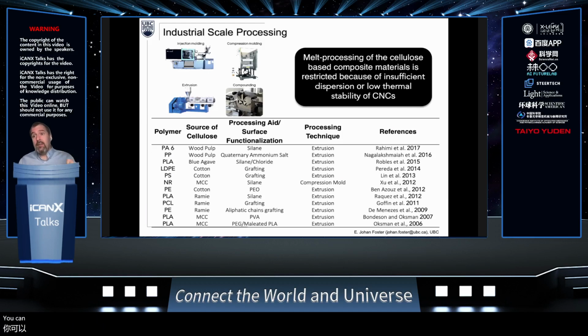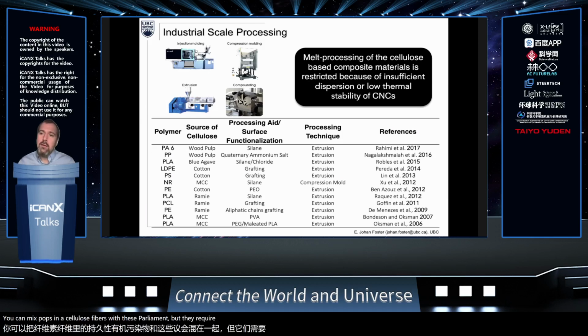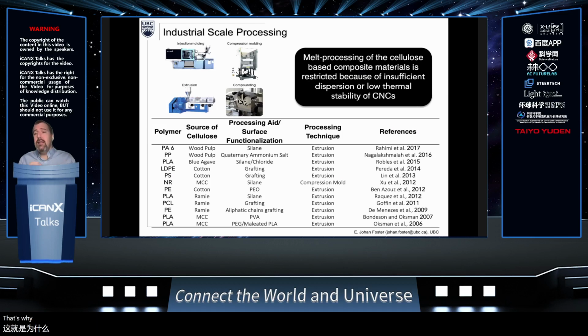You can mix pulps and cellulose fibers with these polymers, but they require some sort of modification. Okay, you can modify the surface with silanes. You can modify them with salts. You can graft polymers on them. You can use mixing aids to allow that extrusion. Lots of great papers out there from anywhere between 10 and say 30 years ago. Okay, the problem with using these aids is they disrupt the interactions between your fibers. That's why it allows this to work. It allows it to be dispersed.